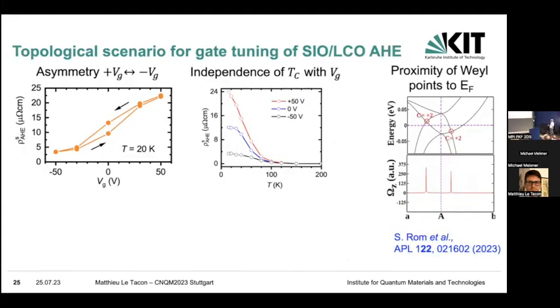And that's pretty much my last slide. You can see that the effect is strongly asymmetric. So it's not the same to make a positive or a negative gating here, because you don't start from 0, so it's not centered at 0. And you see that the onset temperature of the magnetism doesn't depend really on the applied field.